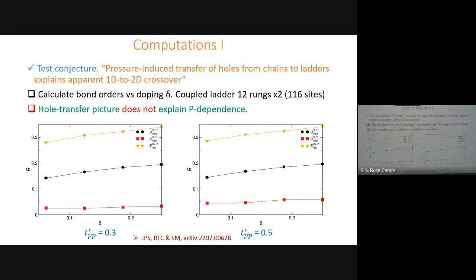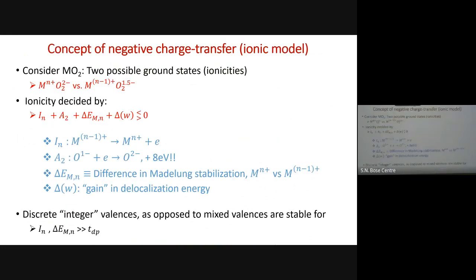If anything, the effective dimensionality, this divided by this, decreases. The anisotropy increases, and the Kojima reference actually experimentally did magnetic stability, and they said the anisotropy might increase the entropy. And that's exactly what we find. So this is not it. This is not doing the dimensionality transition. In the paper, you can see this is almost flat and doesn't work. So now comes the hard part.